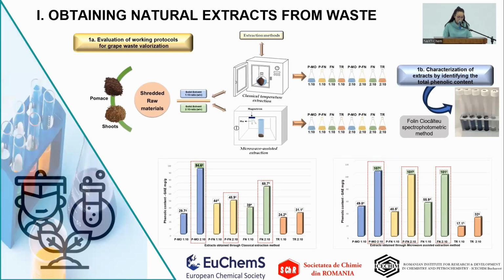As mentioned before, the first step was to obtain natural extracts from waste with increased yields of phenolic compounds, and the raw materials selected were two types of grape pomace and two types of grapevine shoots. After the raw materials have been shredded, two solid-liquid extraction methods have been applied, a classical one using an oven and a microwave assisted extraction with a microwave digestion system, using two solid-liquid ratios of 1:10 and 2:10 weight per volume between the raw materials and the solvent.